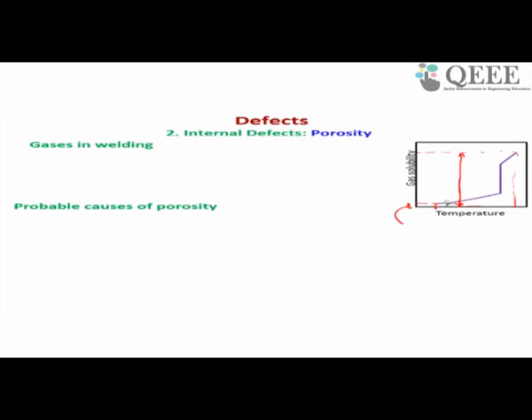These gases have high liquid solubility, and high solubility at high temperature. For example, the molten state is a high temperature state, so these gases have high solubility. However, when the molten metal solidifies, these gases have very low solubility. As a result, the gases will try to escape, and in that place you will get porosity. This is the origin of porosity in welding.